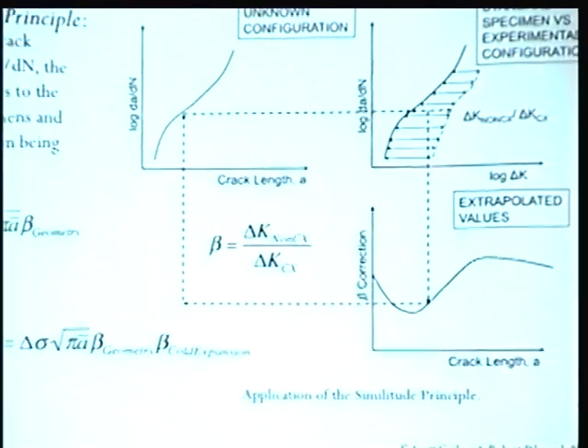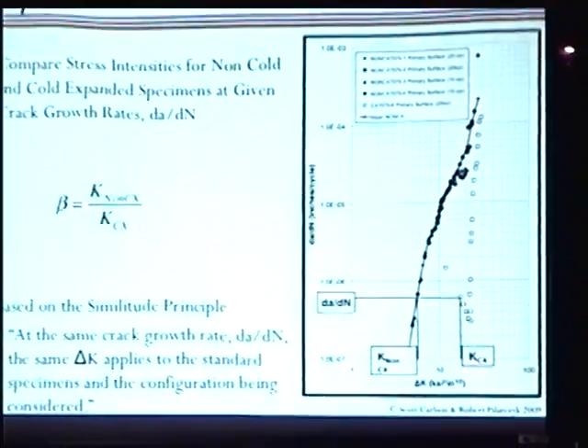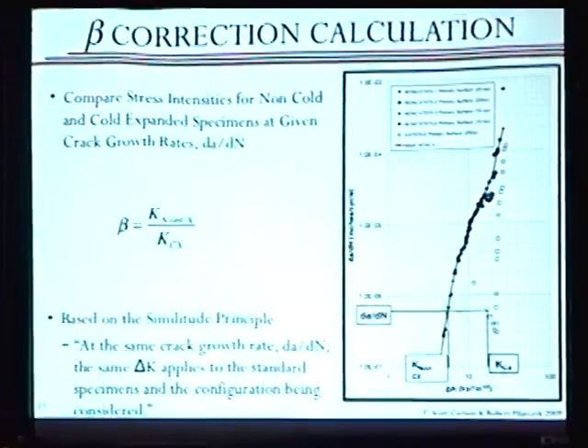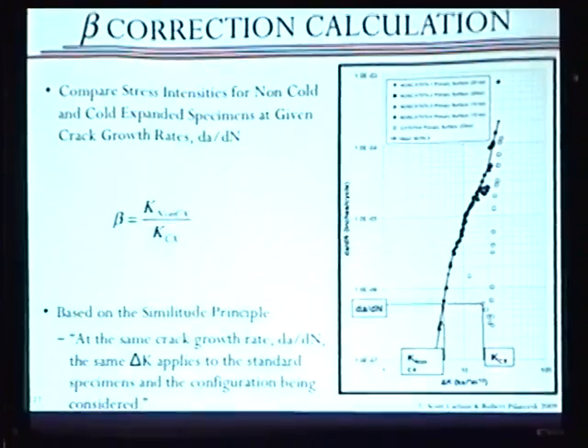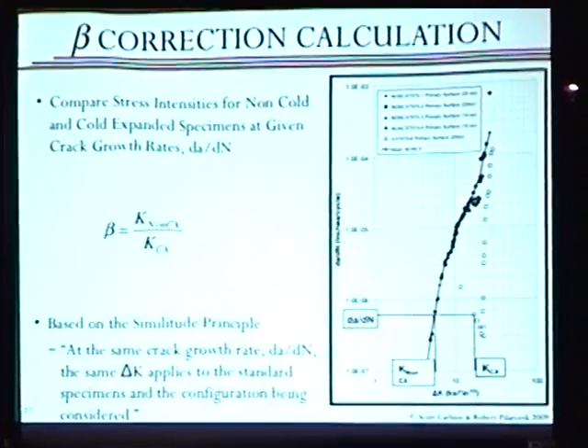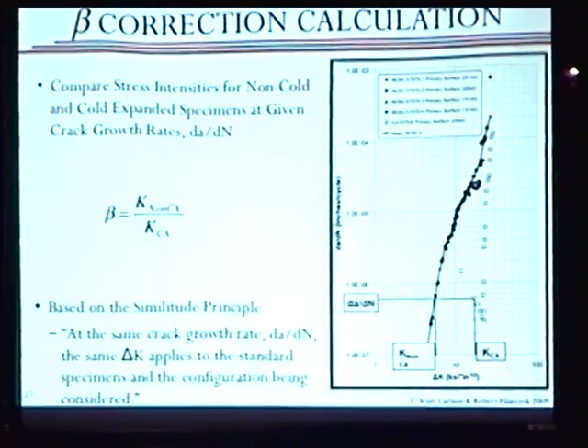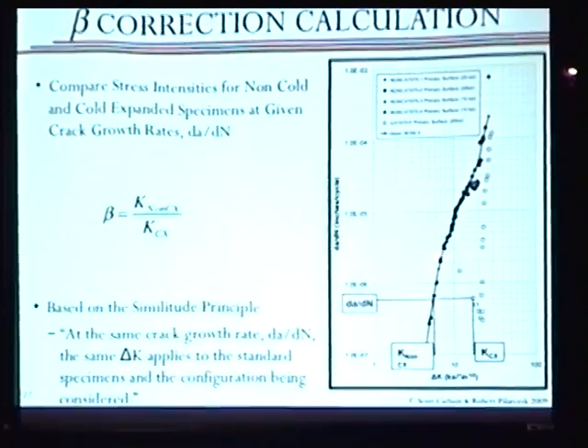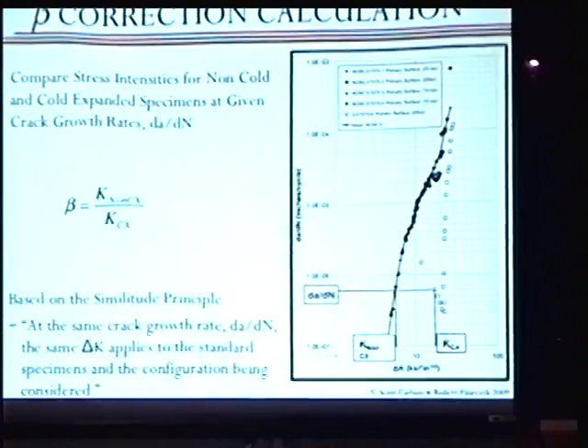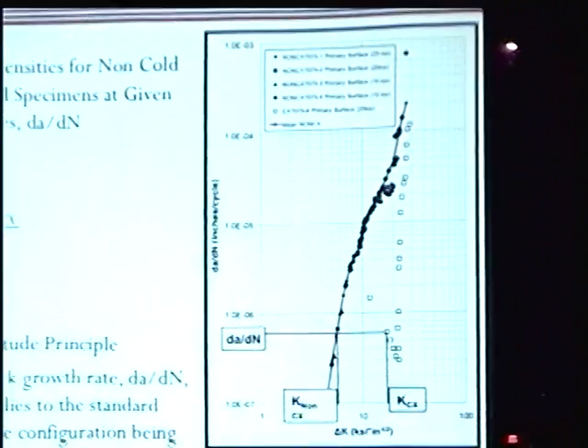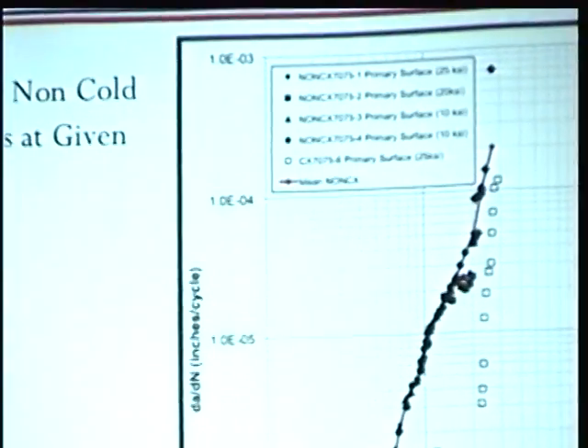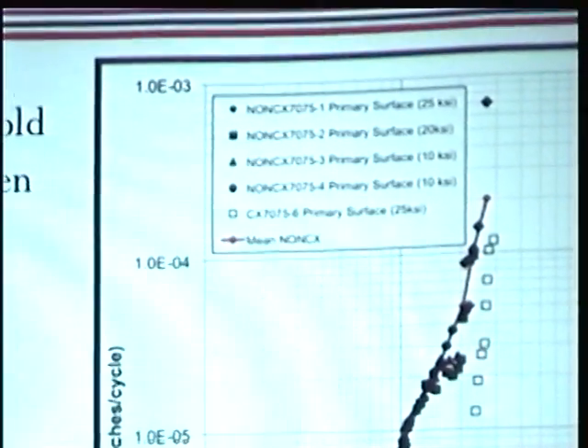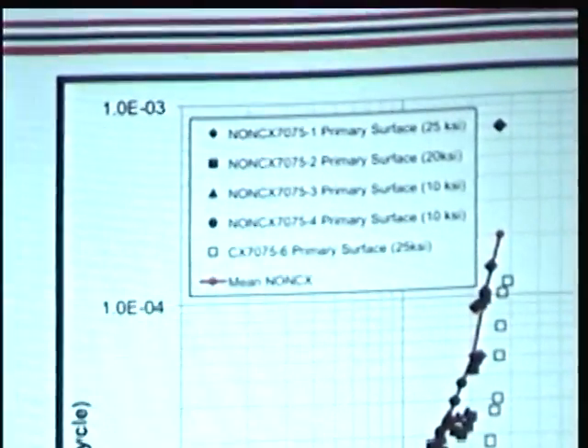So if you go to the next slide, Scott, this is another way to view it. What I've got here is crack growth rate versus stress intensity. And this curve is actually my baseline. That's what I would expect from just a standard specimen, open hole, no cold working process. This is well established. We've got a lot of data, and that's fairly consistent. So that's what I'm comparing to.